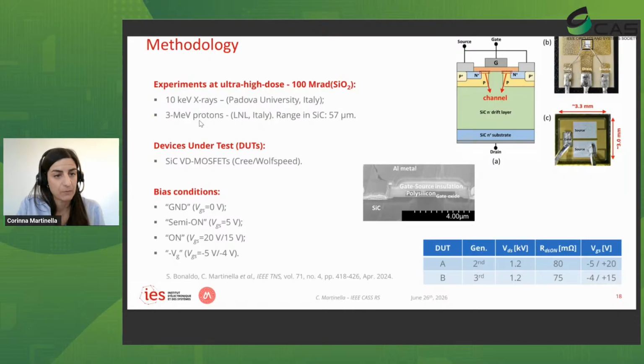These 3 MeV protons have a penetration range in silicon carbide of 57 micrometers, meaning that we are in the substrate. So the majority of displaced atoms are generated in the substrate of the component, because the epitaxial layer is about 10 micrometers, as we said. We performed experiments going up to ultra high doses of 100 megarad in the oxide.